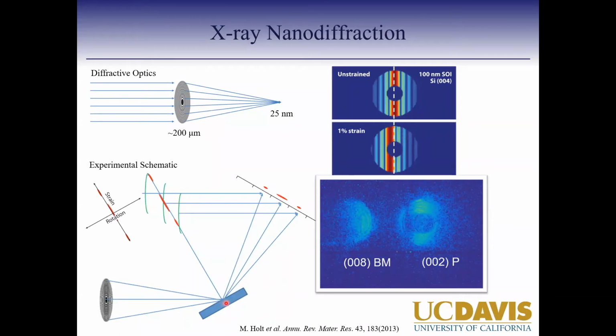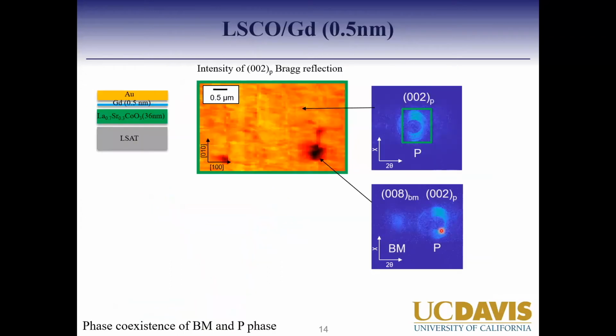In addition, if you have, let's say, two different crystal structures, they will diffract in two different Q space. So if you have the zone plate and your sample with multiple crystal structures, let's say one Bragg peak and a second Bragg peak, that would show up on the detector at a different location. You'll have a perovskite peak right here, and the brownmillerite peak will show up at a different Q location altogether. So at the same time in a sample, you can map exactly how much brownmillerite is present and how much perovskite is present. Once again, the shape is not because of anything to do with the samples, it's purely because of focusing optics. Now that we have that set up, we can scan our samples and start to look at them.